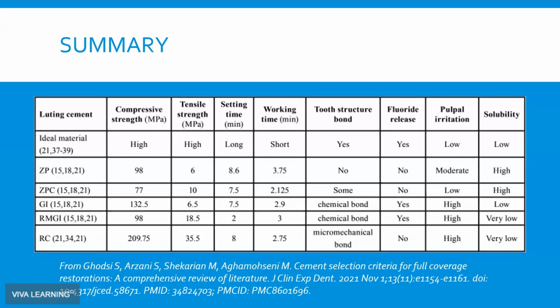Tooth structure bonding. I think at this point, it says resin cement is micromechanical, but that is without a primer. With the primer, depending on the chemistry of the primer, you can have both a chemical and a micromechanical bond. We have the fluoride release, which is debatable how important that is, but obviously many of us would prefer to have it in a margin, not a prosthetic margin. But resin cements did not have that compared to the glass ionomer, the 2 generations of glass ionomer.